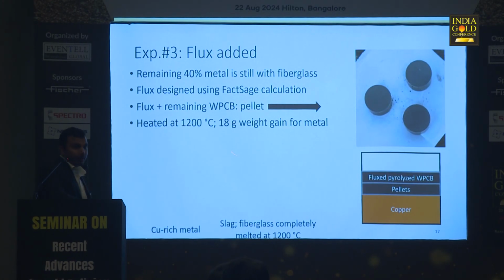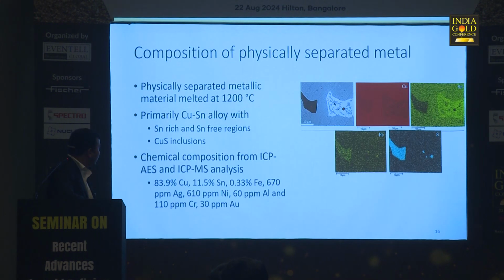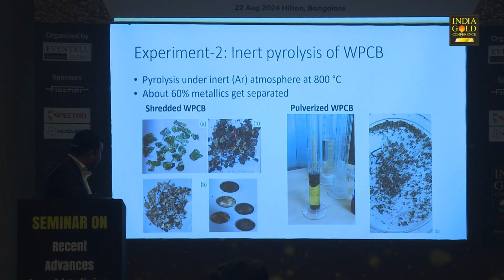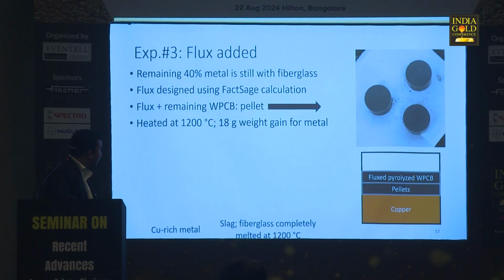Now coming back to the problem of the flux design, where we did all the calculations to design a flux that can be mixed with the remaining amount. Please note that here we had removed the metallics, but some of the black material that you see will also have some metallics. So we want to do further refining. In order to do that, we have to melt the fiberglass. So we did all the mass balance, we designed the proper flux, and then made pellets. You can crush that, make it to powder, and mix with the flux and make pellets. Then we have the copper, which we are using as a collector, and those pellets were placed over it.